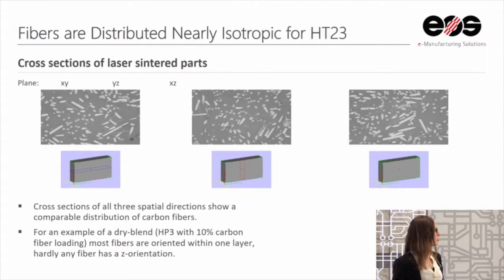And if we look a bit more into detail into how those carbon fibers organize themselves in the parts, we did cross sections at different planes, the XY, YZ, XZ, and so on. If you look at those pictures of those cross sections, you can see the fibers are in all directions. And that is a material we call HT23, and the 23 stands for 23% of carbon fibers we mixed with this PEKK material.